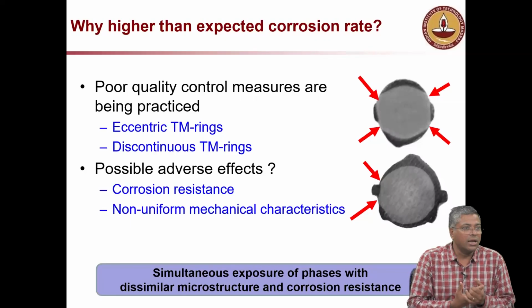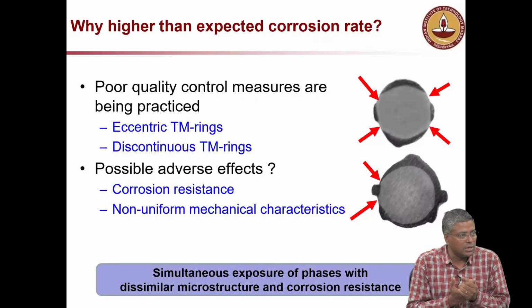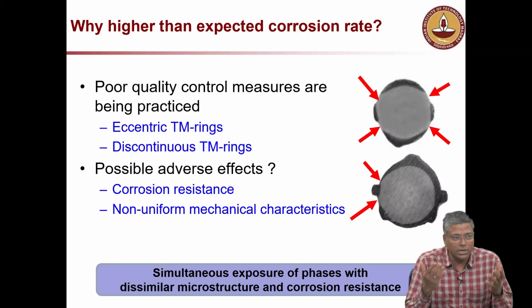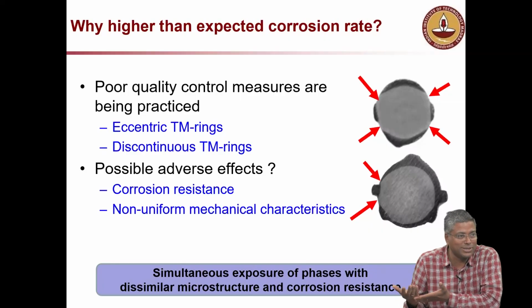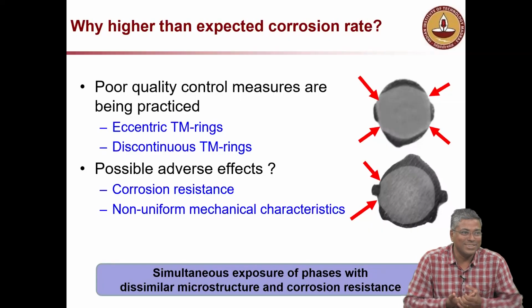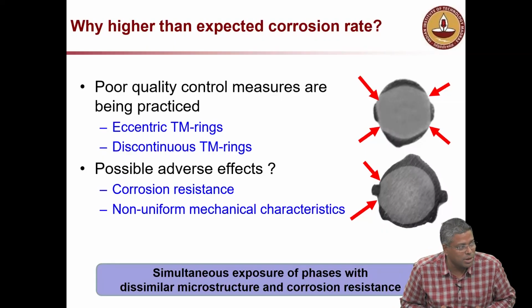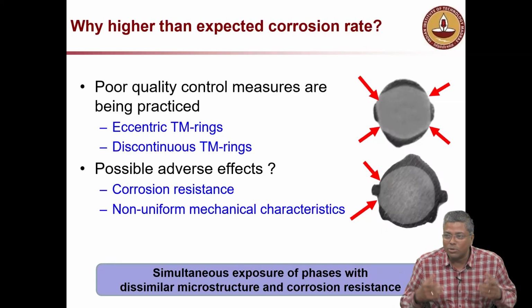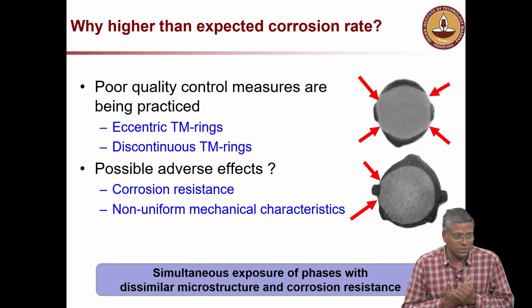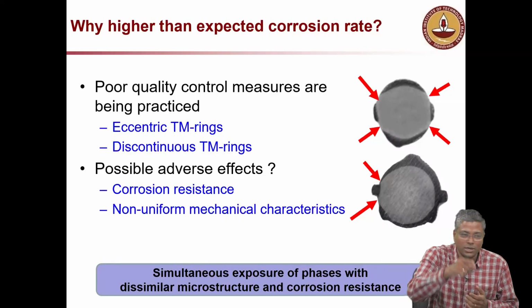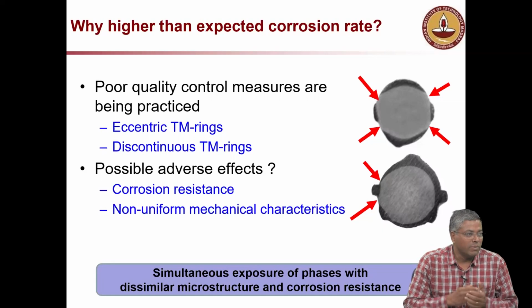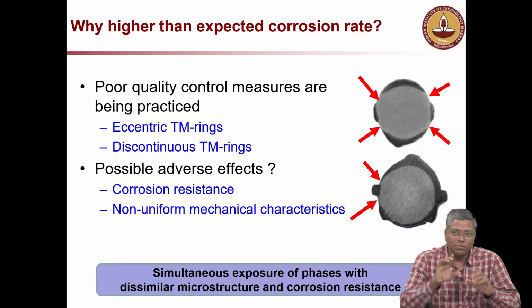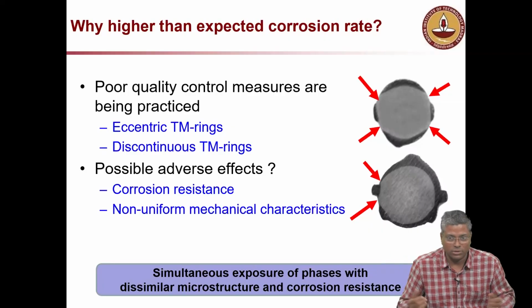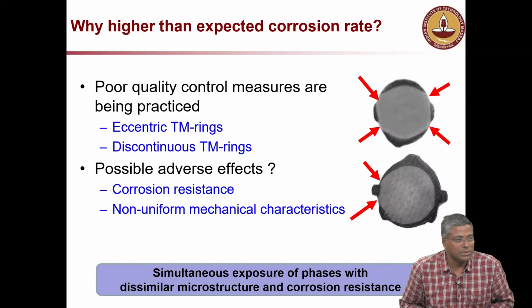So we collected a lot of bars. We did testing in the lab, and we found that TMT bars actually have the same corrosion as the CTD bars. There is no improvement in many of the products in the market. Then we looked at why the TMT bars are not showing good corrosion resistance. The reason is this. When we did the TMT ring test, we found that there is actually no ring on the bars. These are crescents, not rings.